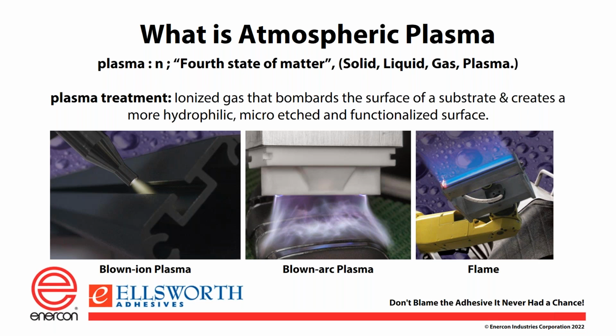And then we have flame. Flame gives you the ability to go much wider, more economically. It also gives you a little bit more area with which you can treat. By that I mean, multi-dimensional surfaces are usually better for a flame treater, just because I don't have to be as accurate with my distance to the surface as I do with plasma. Plasma is very much dependent on the speed at which you're treating and the distance from the surface, and the ion density that you're going to get is related to both of those. Flame gives you a much larger area with which to do that, and with a multidimensional surface like maybe a Coke bottle, where you're trying to treat the side of it, you can see that you're going to be different distances away. So we go to flame when we do this.